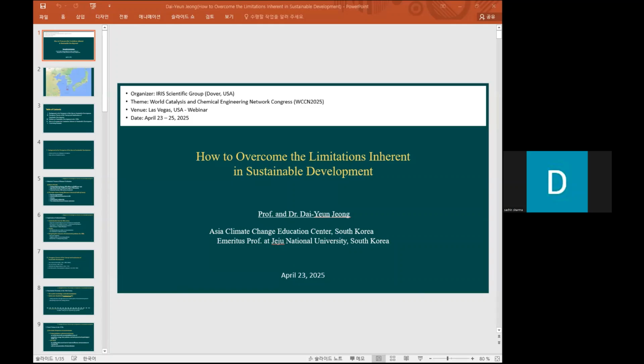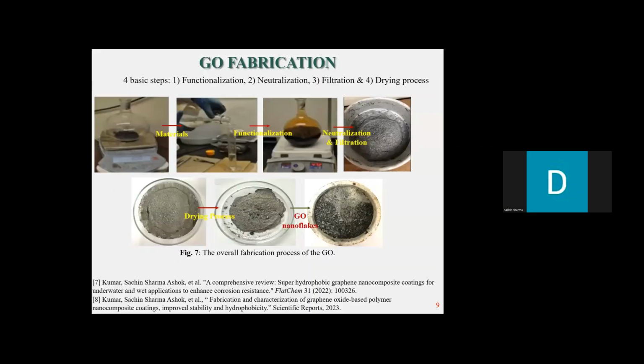Once the functionalization process was done, we need to do neutralization and filtration. We filter using high quality filter paper under the influence of vacuum. The vacuum plays an important role because it needs to completely segregate the nanoparticles from the acidic solution. If you do not use the vacuum, your results would not be good, because large particles will be left on the surface of the filter paper and it will be slightly wet. It will not dry, and hence there will be some kind of cluster, which is not good because when we do the blending process with the resins, it will not disperse homogeneously. The neutralization and filtration was done about 7 to 8 times.